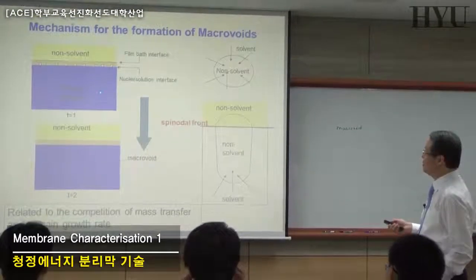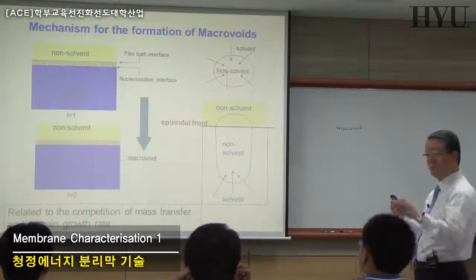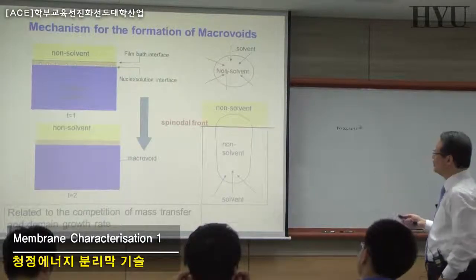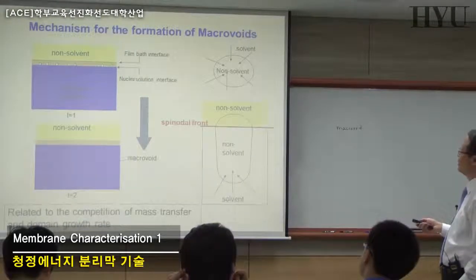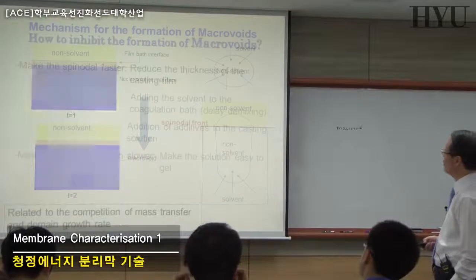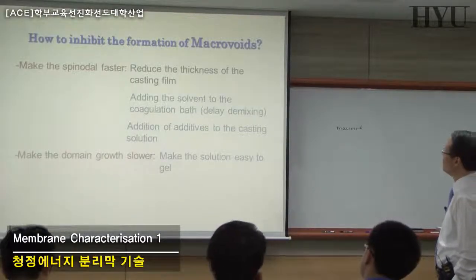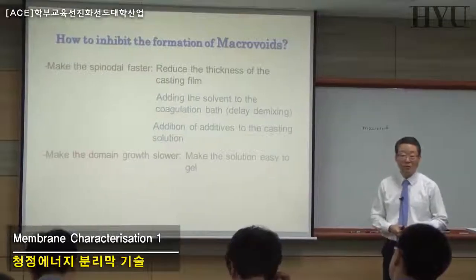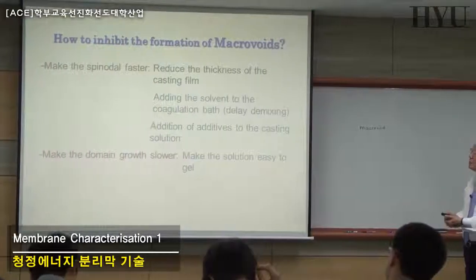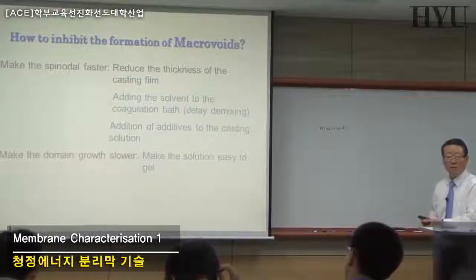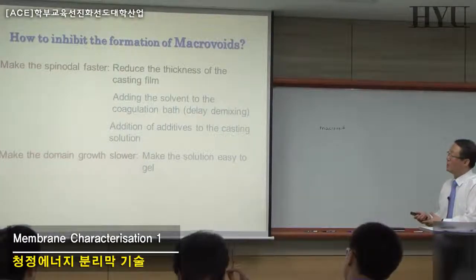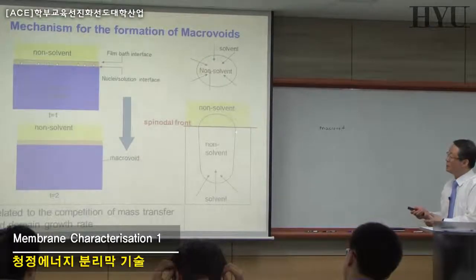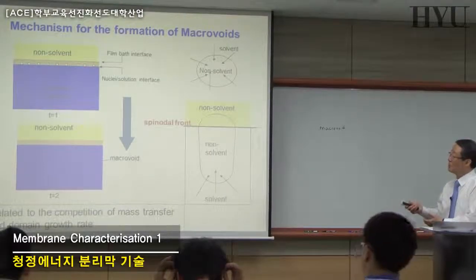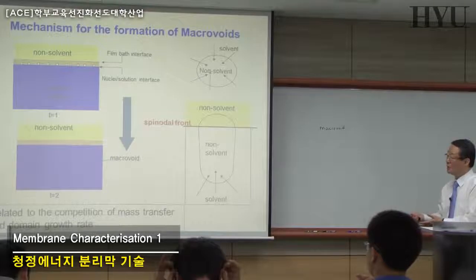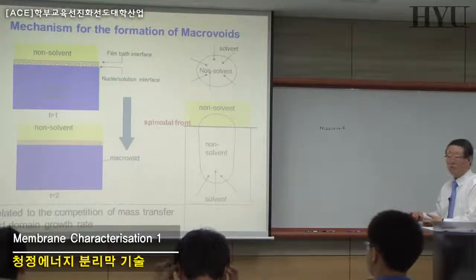So you have a mass transfer from the front, and this is what they call the spinodal front of the growth. Macro void can be avoided by controlling many factors. First of all, you can reduce the film thickness so that the spinodal point should be reached much faster. There is no time to grow because the thickness is very small. You don't have much polymer solution to form the final structure.